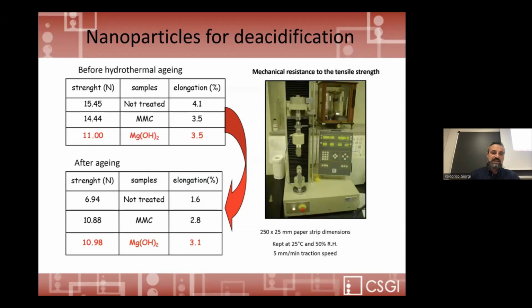Here we have some data about the mechanical resistance, the tensile strength, of samples treated, for example, with alkaline nanoparticles, such as, in this case, magnesium hydroxide. It's interesting to see that paper protected with the application of particles preserved the mechanical properties of paper. Here we have different samples with different tensile strength at the starting point, and you can appreciate the differences after artificial aging. You can see that we have a drop of mechanical resistance for the samples not treated at all. And you can see the benefit of the application of the method.